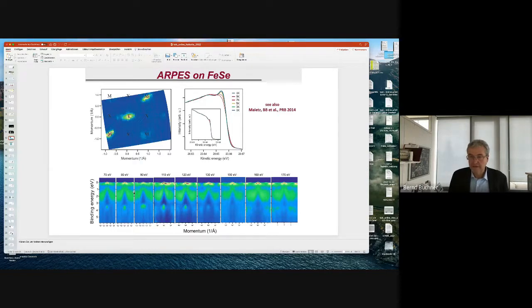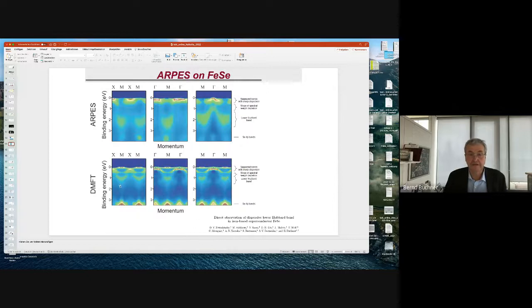And it turns out that this stuff which you see at higher binding energy is characteristic, and these are really features which you can assign to something that I would call a lower Hubbard band. And this comes from the fact that it's not found in these band structure calculations, but it is found in calculations where you model these electronic correlations due to the Coulomb correlations at the iron site, for example, by DMFT. This is just a comparison of these model calculations, so theory and experiment.